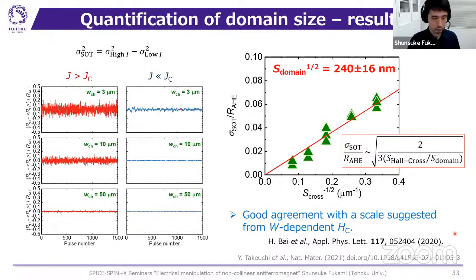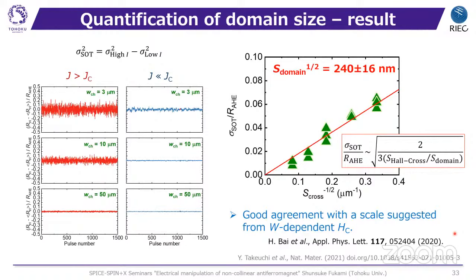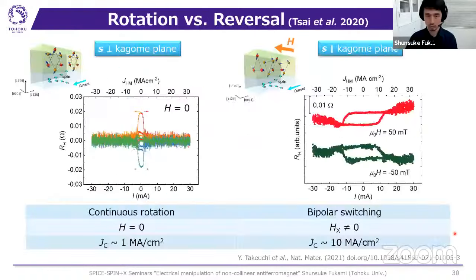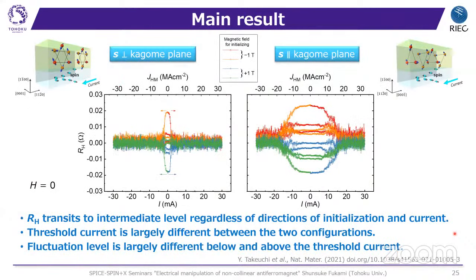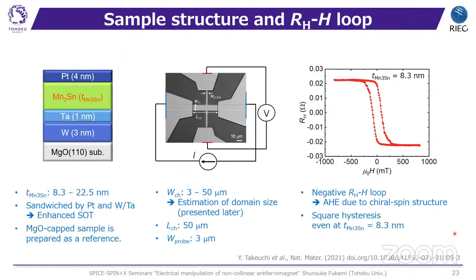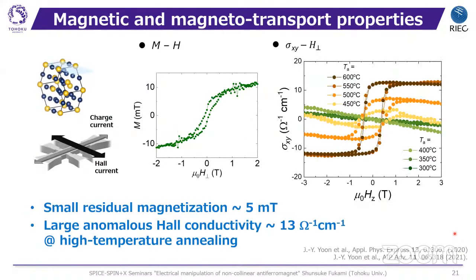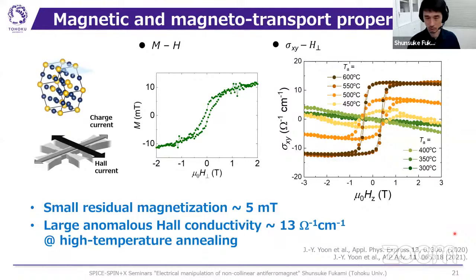Okay. So then the second question is, I think in the first part you had different annealing conditions for the manganese tin films, and I was wondering whether the domain size changes depending on the annealing condition. I saw the anomalous Hall effect was small for the lower temperature annealing, and I was wondering whether that's also an effect of the structural or magnetic domain sizes. I think that's a good point, and we didn't examine it, but I guess that the domain size should change with the annealing temperature. Okay, thank you.